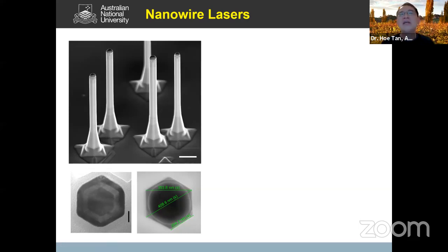One of the critical issues in gallium arsenide is that the surface has a very high surface recombination velocity, a lot of surface states. If you don't passivate the surface states, they act as non-radiative recombination centers, which will essentially reduce the lasing efficiency of your nanowire. So we clad this gallium arsenide core with an aluminum gallium arsenide shell, okay?